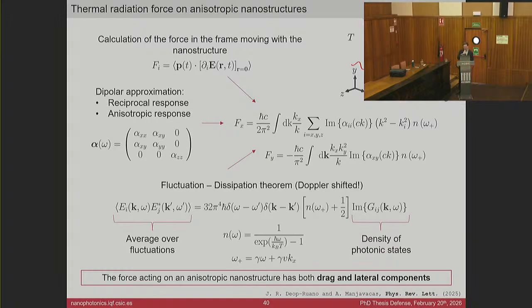So basically, I'm going to try to illustrate it with the pointer. If you start with your particle oriented in this way and it's moving in this direction, what it will do is that it will start moving until the trajectory is aligned with the long axis where it has the maximum polarizability, and then it will move in that direction until it stops because of the drag force.